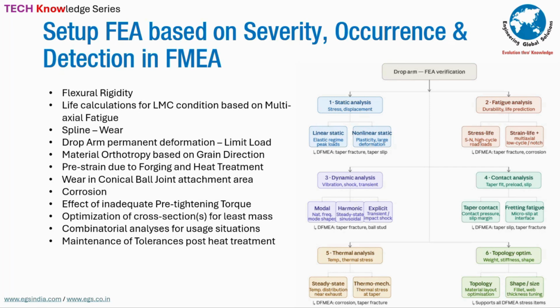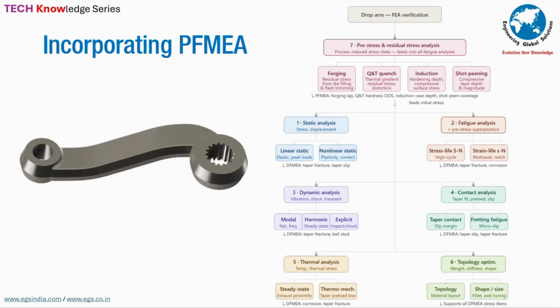So the combinatorial analysis needs to be done for the usage function requirements based on design of experiments. And then the maintenance of tolerances post-heat treatment can all be studied using finite element analysis. Only when you put this together and look at the risk factors does your result become accurate in terms of predicting the reliability and the performance of the unit in real world life. So incorporating the PFMEA, you put it upfront: residual analysis, forging, quenching and tempering, induction, and then shot peening. You put that together and then you do all your analysis inside. Your inherited stress state comes in. It gives you a better picture.